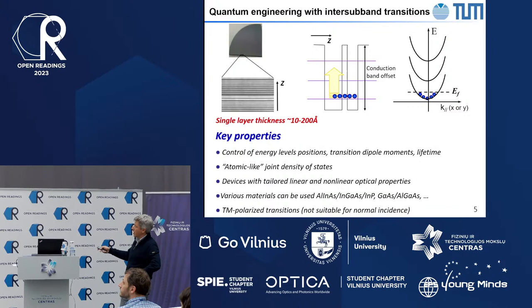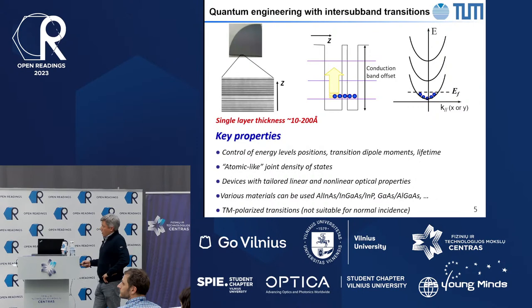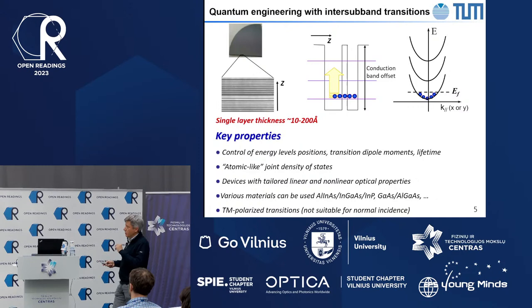And if all the effective masses for all the states are roughly the same, then these transitions all occur from this parabola to that parabola at the same energy. So you have an atomic-like joint density of states, which means that you can dope your structure heavily, and all these electrons will essentially transition at the same energy. You can tailor this structure to have desired linear and nonlinear optical properties. And what's important, you can implement what you designed with very high precision using the existing growth techniques that were developed for semiconductor lasers. So the technology to implement this is all available.